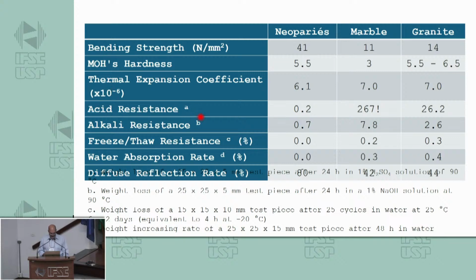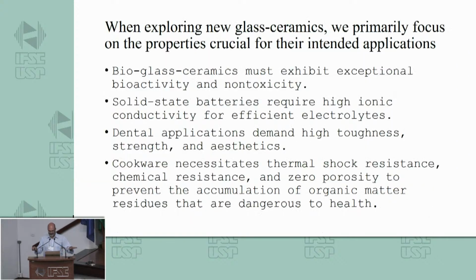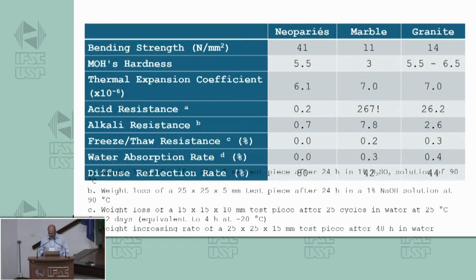Alkali resistance is, again, very low. The freezing and thaw resistance is the best. Water absorption, 0. And this diffuse reflection, the surface aspect, is very high.